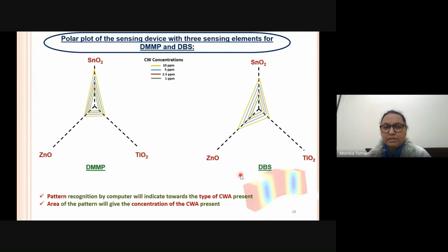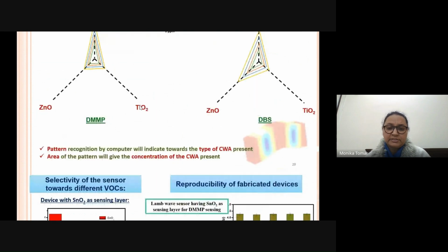Then we did the polar plot for the sensing devices with the 3 sensing layers, and we got different patterns for DMMP as well as DBS. And as the concentration is increasing, the area of these patterns is increasing. So using this E-nose, we can detect the presence of different chemical warfare agents in the warfare.